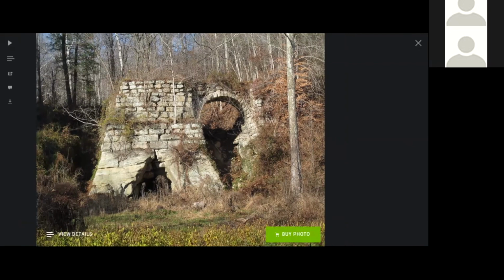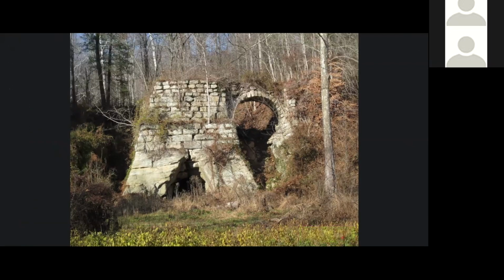Now, when you look at this, you'll see that this furnace is surrounded by trees. And notice that they're not really thick, like 2 or 3 feet in diameter. They're all fairly small trees. And this would have been the case even 100 years ago, because these charcoal furnaces required a tremendous amount of woodland around them that they needed to harvest the wood to make the charcoal. So you would have a furnace, and then several miles around it, you'd have almost barren stretches of landscape because you had to take down all these trees and convert them into charcoal. So it really was not a sustainable practice.